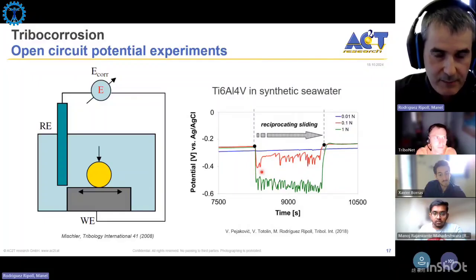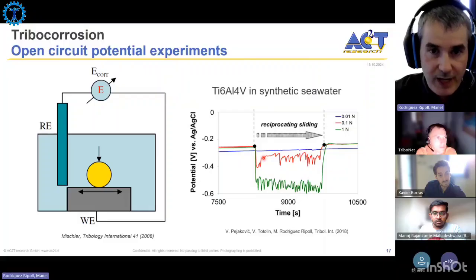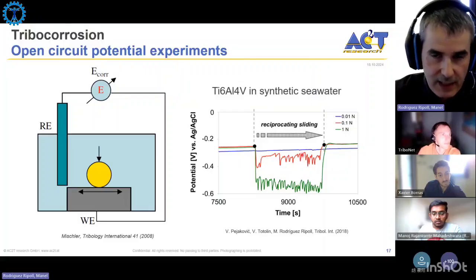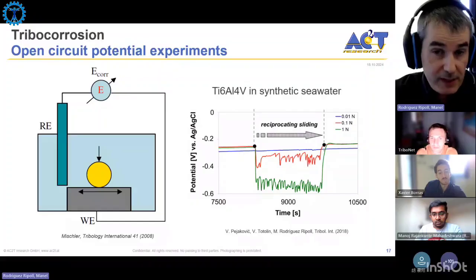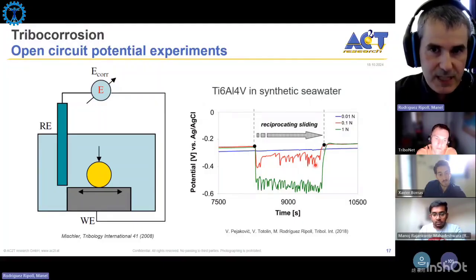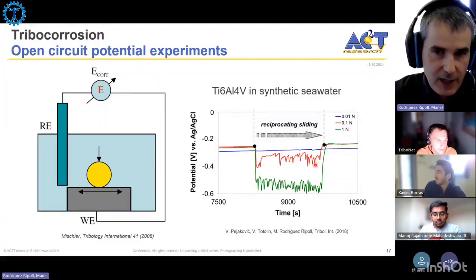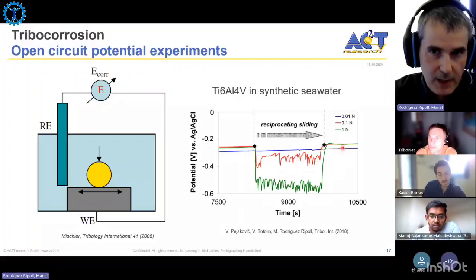The depassivated area tries to repassivate again, so you have these instabilities here, and at the end of the experiment, the open circuit potential returns to the initial value because the material is repassivating. So basically, you are in the same electrolyte, so the material spontaneously builds up again this passive layer that was mechanically broken, to establish the same equilibrium condition as at the beginning, having the same potential as before sliding.